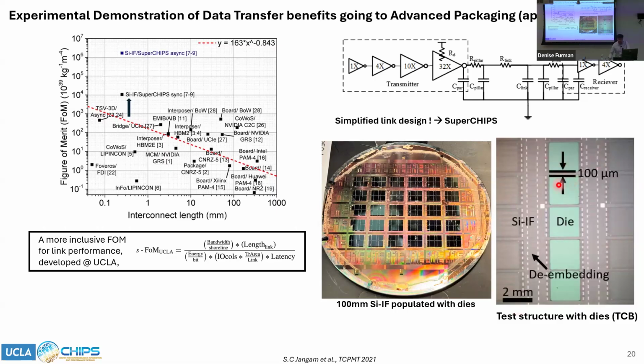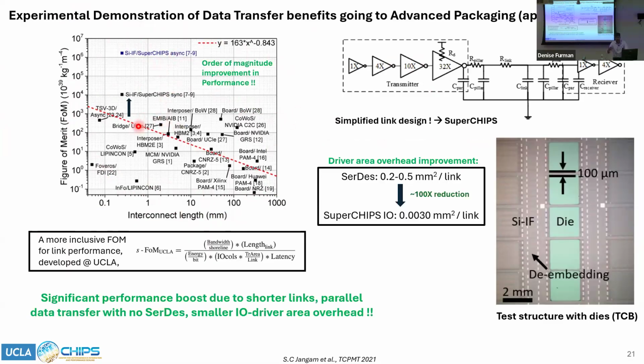And because we use bare dies, you see how the inter-die spacing can be less than 100 microns. And also because you have, like I mentioned before, a large number of parallel links and very short links, you can treat the link itself with an RC model, and therefore your driver design becomes just simple cascaded inverters. And you can see here how this approach significantly improves the performance metric, or the figure of merit, of the link itself. So here you see a comparison between various communication protocols and technologies on the board versus the Superchips protocol, which is what we call our high density protocol. You can see that you get an order of magnitude improvement in the performance of the links. And you also get a 100x reduction in the area overhead of the driver itself, because you're now going from a SerDes to a simple CMOS-based cascaded inverter chain.